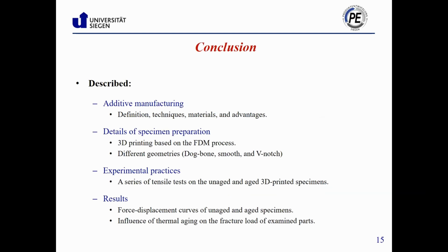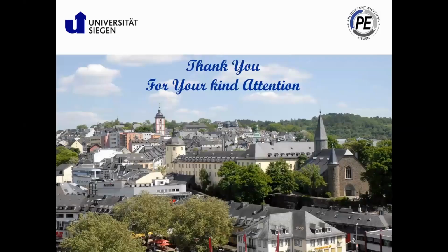As a short conclusion, I would like to review the presentation briefly. First of all, additive manufacturing and advantages of this manufacturing process were described. In the second section, details of specimen preparation were presented, where we used the FDM technique for fabrication of the specimens. In description of the experimental test, details of accelerated thermal aging and series of tensile tests are explained. Finally, as a result, we have demonstrated force displacement curves of aged and unaged specimens with different geometry, which show accelerated thermal aging can lead to a decrease in the strength of 3D printed components. Thank you very much for your attention, and let me know if you have any questions.